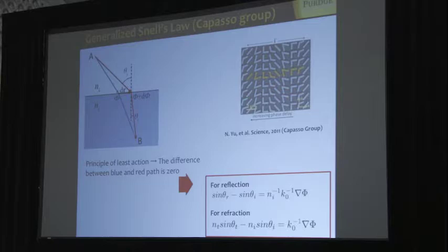If I place tiny antennas, which could be much smaller than the wavelengths, on the interface, and each antenna couples to light and shifts the phase abruptly because of this coupling. And the shift would depend on the position because the antennas are different. So I would introduce the gradient of phase. But gradient of phase means momentum. So to conserve the momentum of the photon, now we have to take into account the momentum introduced by these antennas.